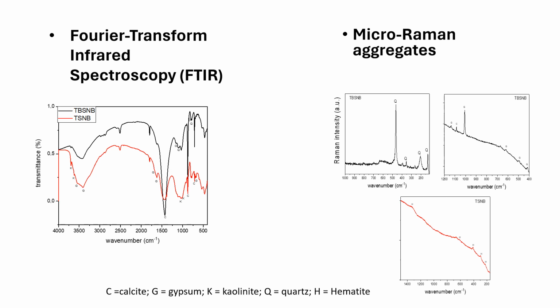Therefore, from the results, it can be deduced that the samples are lime mortar with aggregates of different nature, quartz and gypsum. In addition, sample TSNB shows pieces of ceramic materials and the presence of hematite. These results are consistent with those of visual and optical characterization. Kaolinite has a very low Raman scattering, with a small signal at 130 centimeters minus 1, so it is very difficult to identify this compound by this technique, and normally other components are more easily identified, even if they are in lower concentration, as is the case of iron oxide.